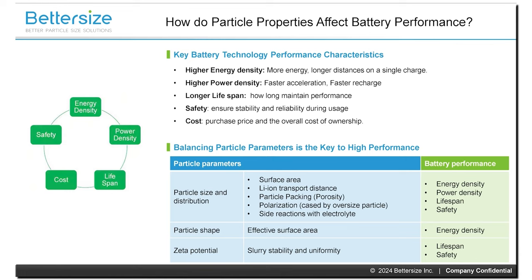Particle size distribution: if we control the particle size distribution, we can ensure a uniform electrode packing and efficient ion transport. And this would optimize battery performance and energy density. However, having a relatively broad particle size distribution combined with spherical shape of electrode particles can help to obtain a higher specific charge capacity and higher energy density. So it is important to consider the benefits and the adverse effects in real applications and flexibly adjust the particle size and particle size distribution of electrode materials to meet the requirements for different application scenarios.